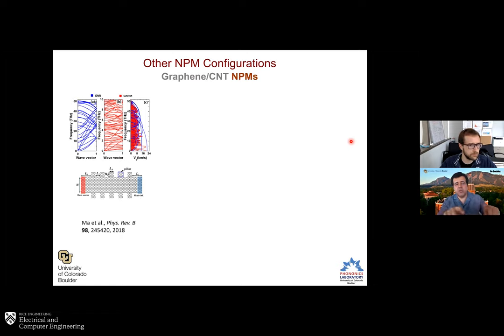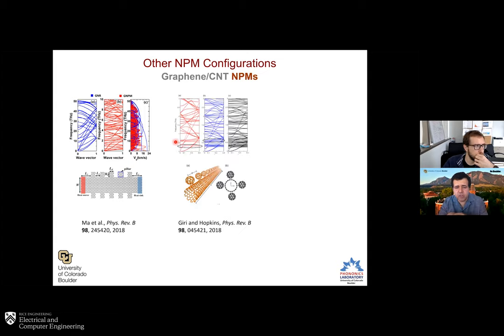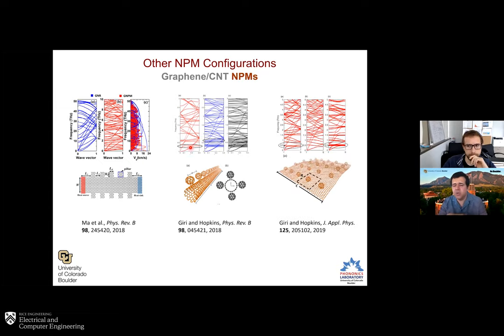So this group has shown that you can have a nanoribbon of graphene with legs extruding. And again, you see that same effect there in the dispersion. And from Virginia, they have buckyballs distributed over a carbon nanotube, and these buckyballs produce the resonances. And the same group realized the same idea with buckyballs and graphene. And again, you can see the resonances.